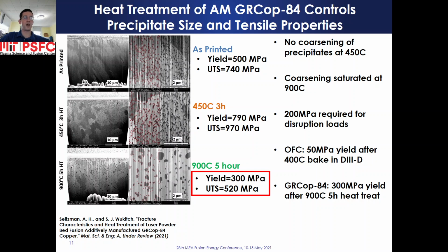However, oxygen-free copper would anneal to 50 megapascals after a 400 Celsius bakeout in D3D, preventing its use. As precipitate coarsening in GRCop-84 has saturated after the selected 900 Celsius 5-hour heat treatment, no changes in material properties will occur during the bakeout, and the 300 megapascal yield strength meets disruption load requirements.